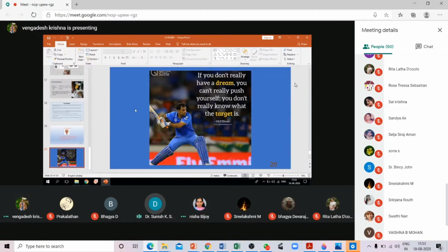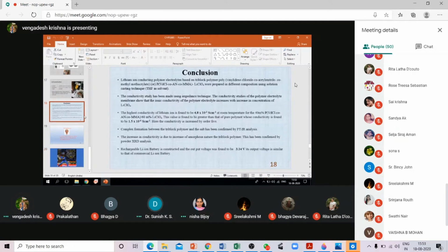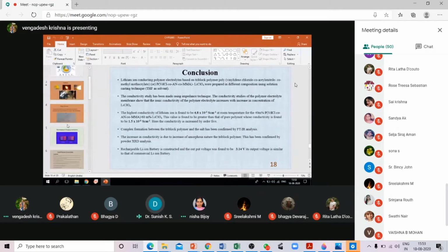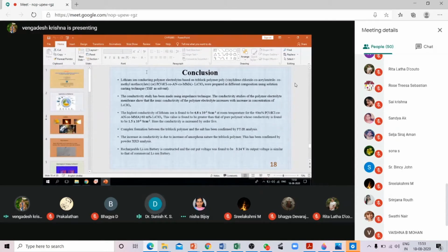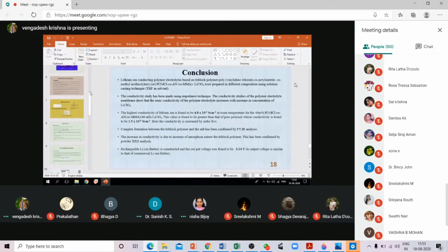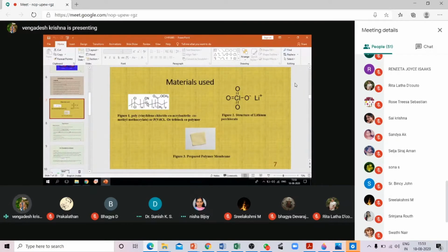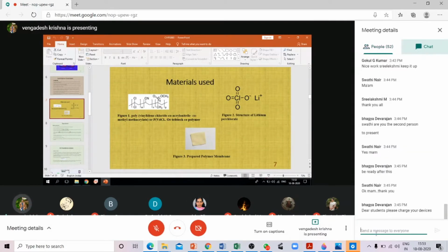When you tried the triblock polymer, it's a conjugated polymer, right? Yes, sir. So why did you select a conjugated polymer instead of a saturated backbone polymer? It is very simple, sir. A single monomer membrane of a polymer will not provide the mechanical strength and the good ionic conductivity. You can see here the nitrile group, CN group, it's called acrylonitrile, which provides the mechanical stability. And the movement of ions is determined by the vinylidene chloride and the methyl methacrylate group, especially the carbonyl group present here, which forms the complex, like a hopping mechanism, and allows the ions to move between the cathode and anode, sir.